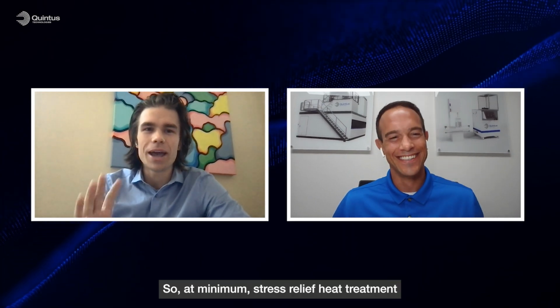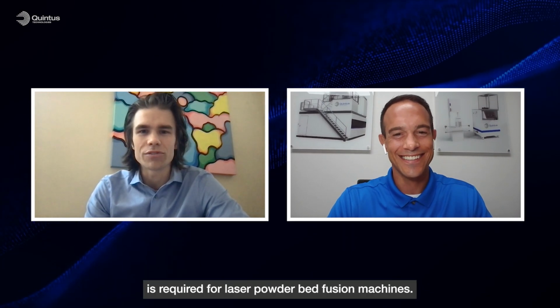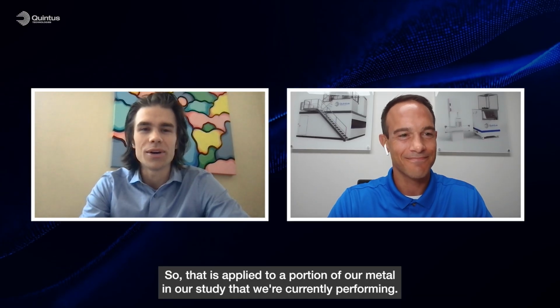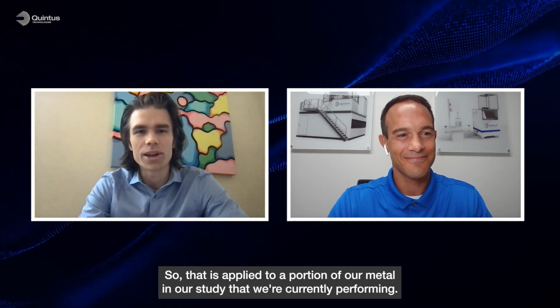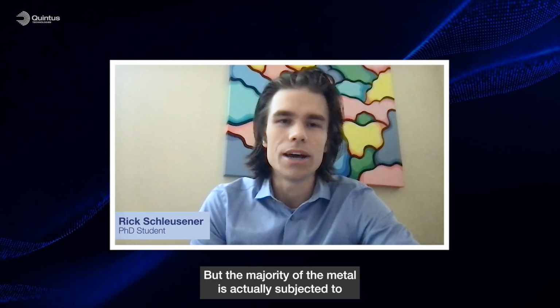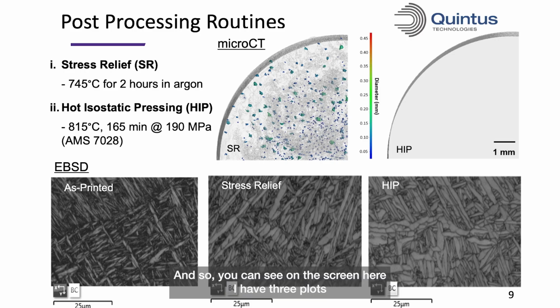That's correct. At minimum, stress relief heat treatment is required for laser powder bed fusion machines. That is applied to a portion of the metal in our study, but the majority of the metal is actually subjected to a low temperature, high pressure HIP cycle, courtesy of Quintus Technologies. You can see on the screen here 3 plots showing EBSD band contrast images that show the relative grain sizes for each of these heat treatment conditions. And you can see that the HIP process is actually coarsening our grains, which is beneficial overall.